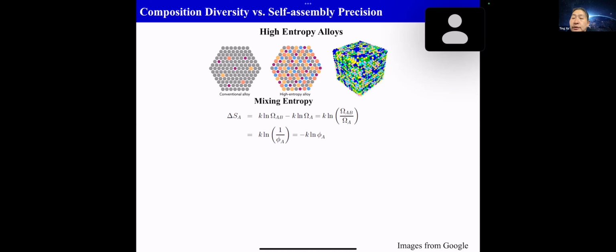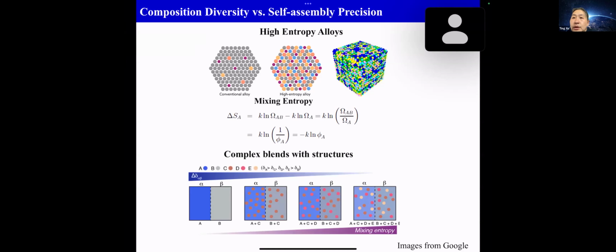And they do have this formulation flexibility. This is really amazing about this entropy driven phase behavior. And we have been thinking about whether there's a way to really take advantage of this entropic contribution. And we deal with entropy all the time. You have that associated with polymer chain conformation. But we want to think about whether it is possible to introduce the concept into this structured system. That means you have some building blocks in the system and it's going to form this type of structure.